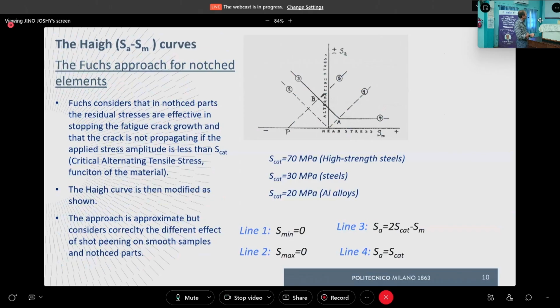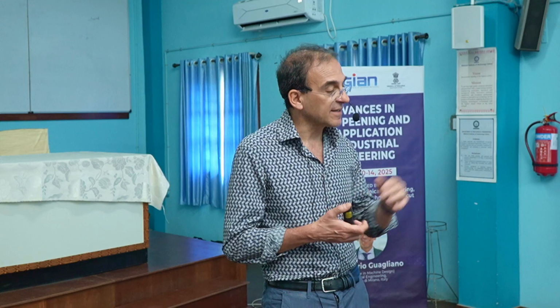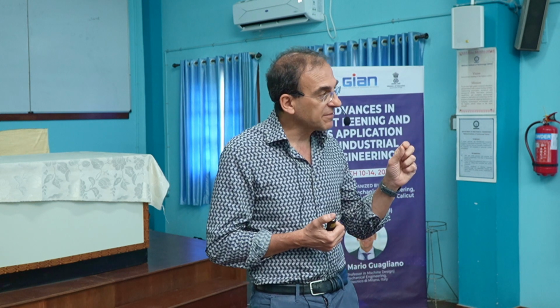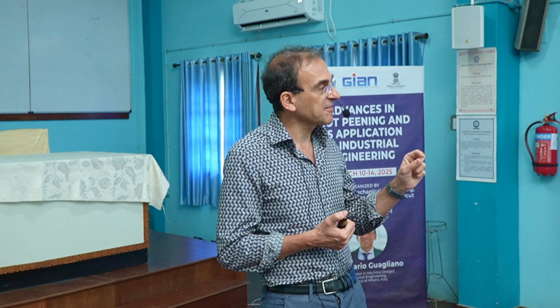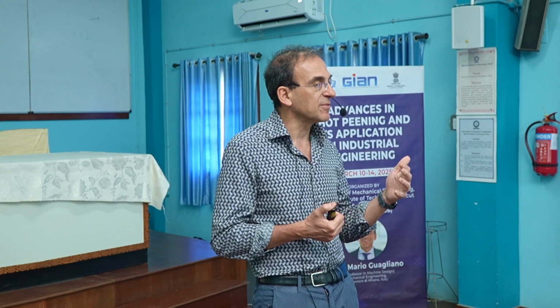And here is the estimation of this S-cat for three different materials: high strength steels, and aluminum alloys, 70, 30, and 20. Okay? And the Haigh diagram is defined this way. Line 4 is the line that defines S-cat. What does it mean? That if the amplitude exceeds S-cat, propagation will appear, and so we are not able to stop the already originated crack. But if the amplitude is less than S-cat, it means that the fatigue crack will stop.